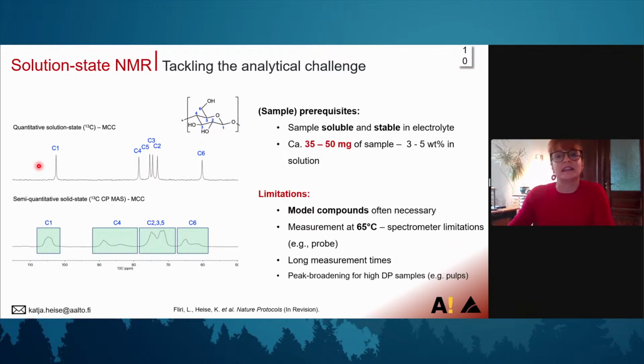And this is something that the NMR expert, of course, has to check whether, for example, the probe is made for these high temperatures. We have relatively long measurement times, depending on which 1D and 2D NMR spectrum I want to acquire. So it can be up to 12 hours. And if we have pulps, for example, in high molecular weight, we might observe peak broadening, but I will come to this also a bit later.